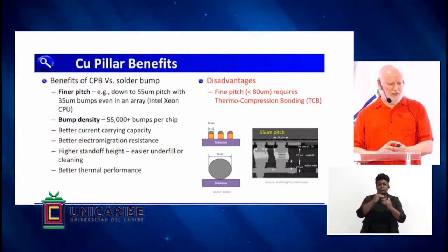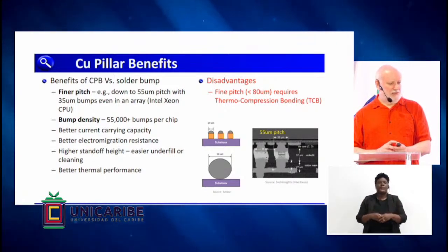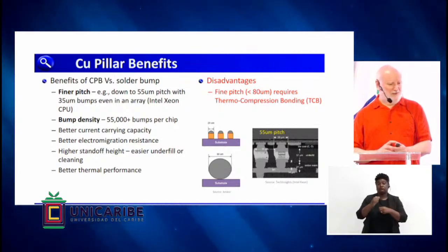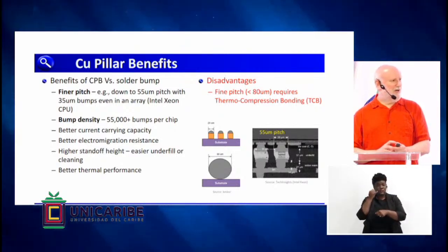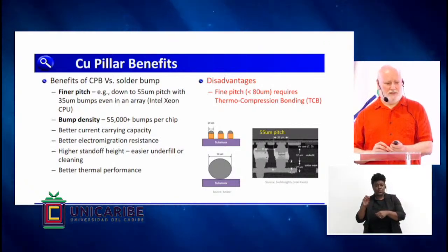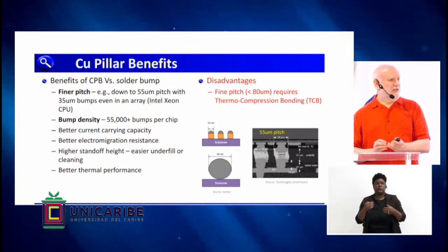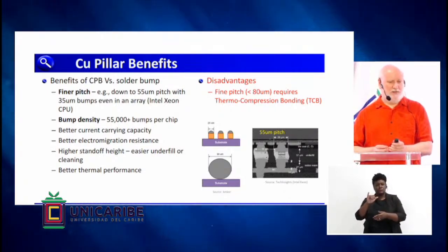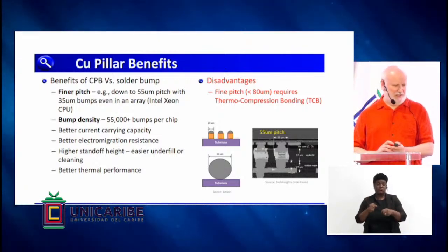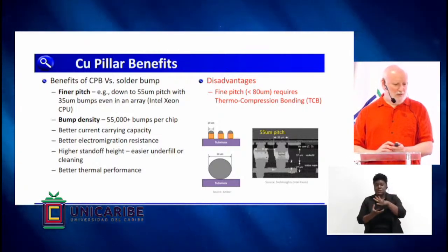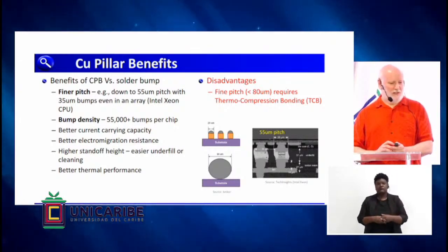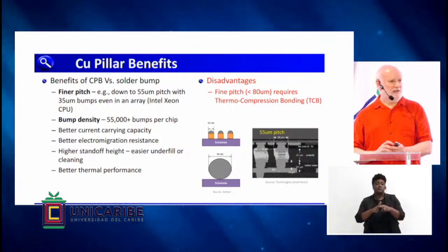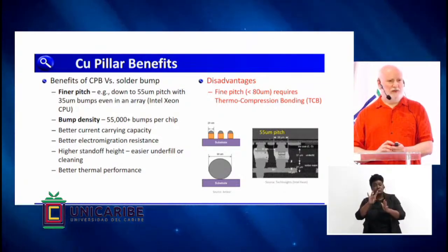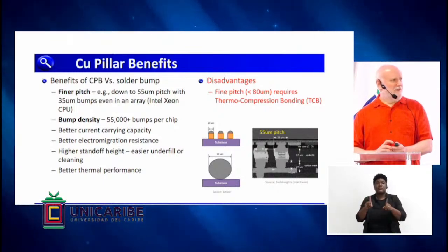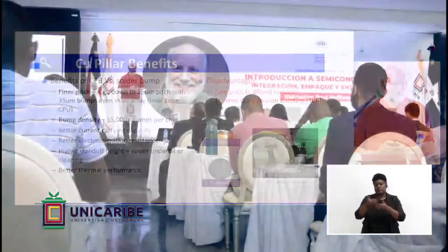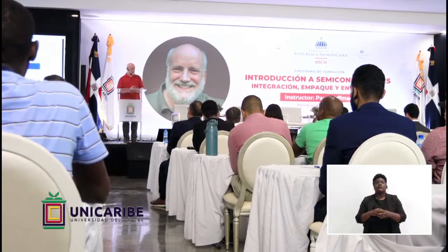So the main reason to use a copper pillar bump is for finer pitch. So you can shrink the pitch down to 55 or 35 micron. You can have high bump density, tens of thousands of bumps on a chip. Good current carrying capability, good electromigration resistance, which is a particular type of failure that can occur. But the downside is, with respect to pitch, if you go below about 80 microns in pitch, you have to change the joining process, from what we call a mass reflow process in an oven into a thermal compression bonding process where we're doing one chip at a time.